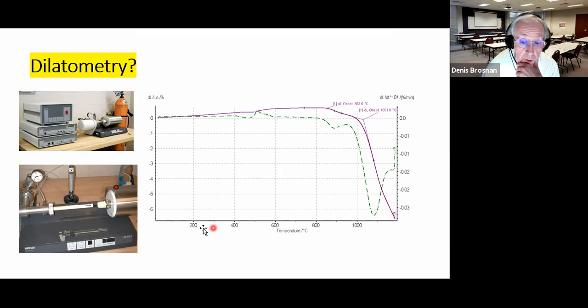On this graph, we show around 6% or so shrinkage. That's really too much shrinkage in a practical sense, because it's hard to make a ceramic with more than about 1.5% linear shrinkage without its cracking. In the drying course, I talked about the volumetric shrinkage being approximately 3 times the linear shrinkage. And so if you're above about 1.5% linear shrinkage, then you're going to be above about 4.5% volume shrinkage, and that's a lot of shrinkage in the ceramic.